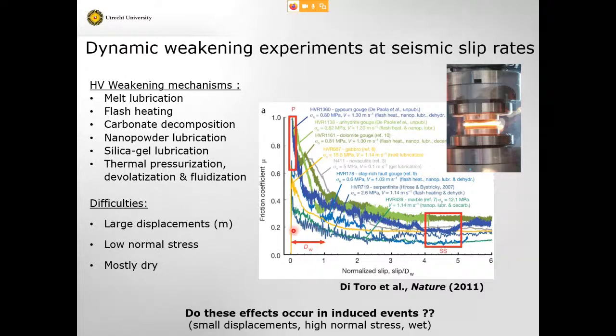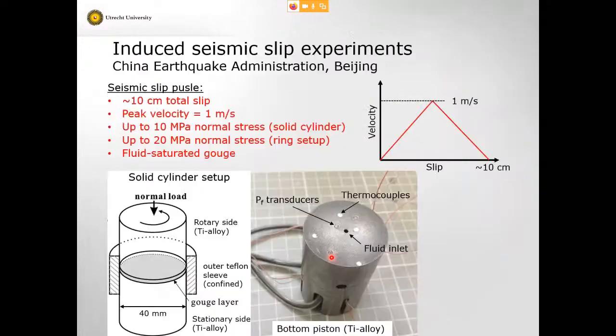We also did very high velocity friction experiments. Some of you will have heard of this kind of work in association with work on natural earthquakes, doing extremely high velocity friction experiments where virtually all materials, if you slide them fast enough, show a huge drop in friction coefficient to very low values around 0.1 or 0.2 because of processes like melting or producing silica gel layers or thermal pressurization of the pore fluid, many other effects. Do these effects occur in Groningen once you start a fault moving?